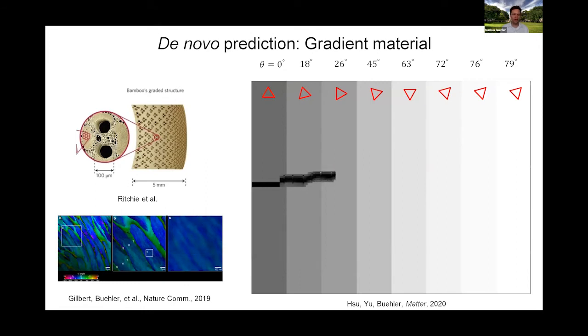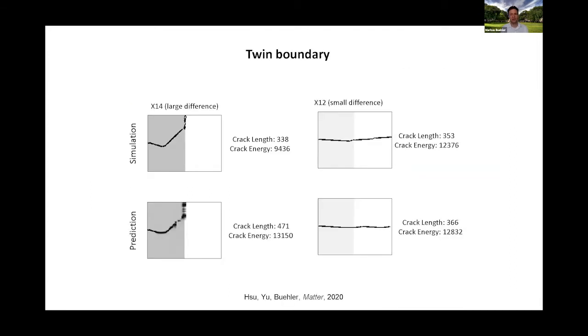And an example here would be gradients. So we have a gradient here, a continuous variation of microstructure. And that is a situation that the model has not seen during the training, but can actually describe very well how cracks propagate in a situation like this, describe the branching of cracks and the stopping of cracks. And this is an example where we picked a few really interesting situations where we see some unique phenomena like the stopping, the arrest of a crack, or the deflection of a crack at, for example, twin grain boundaries.